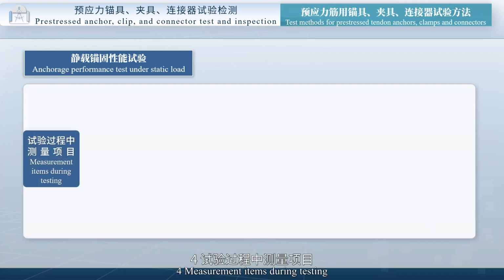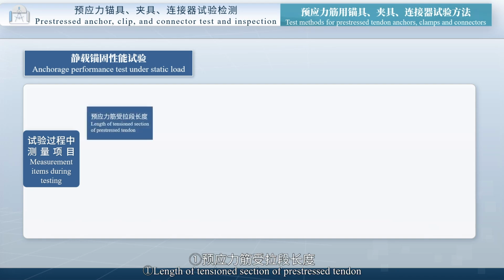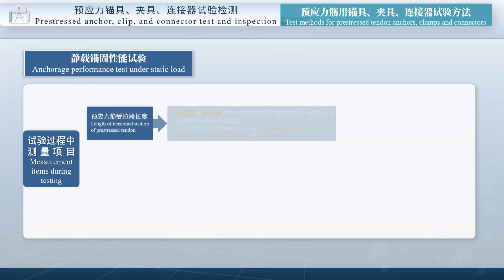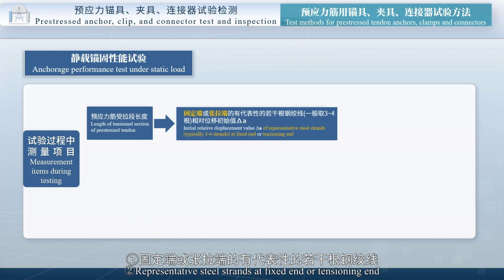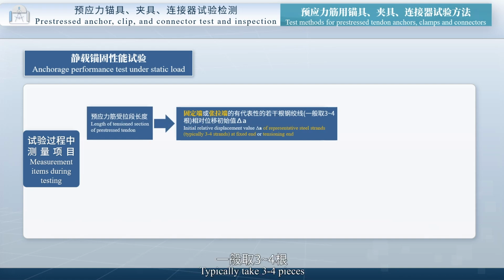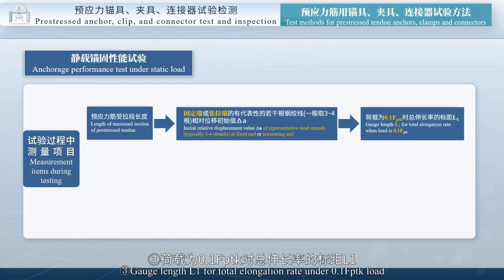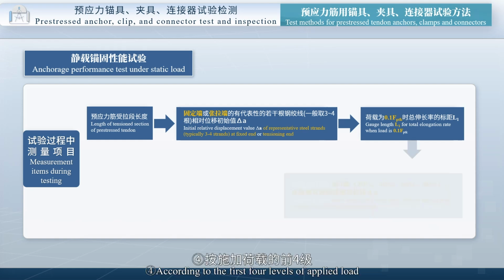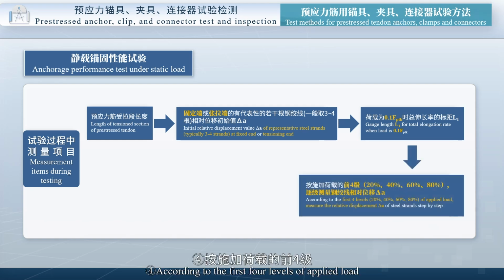For measurement items during testing, first, the length of the tension section of the pre-stressed tendon. Second, representative steel strands at the fixed end or tensioning end, typically taking 3 to 4 pieces, and the initial relative displacement value delta A. Third, gauge length L1 for total elongation rate under 0.1 fptk load. Fourth, according to the first 4 levels of applied load, 20%, 40%, 60%, 80%, measure the relative displacement delta A of the steel strands step by step.